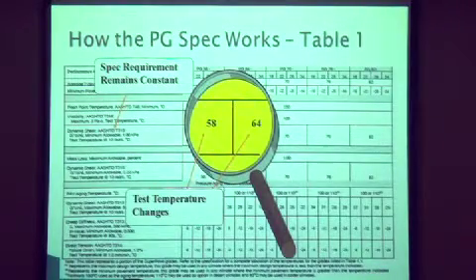The specifications that were produced are in the AASHTO M320, and you have a table where you have these different PG grades, and then what we have is a series of properties in these horizontal tables. So for example, here you have a dynamic shear stiffness. This number here, I know you can't read it on the slide, but it says 1 kilopascal, and the material has to be 1 kilopascal for this particular grade, 58, at 58 degrees C. This particular grade, it has to be 1 kilopascal at 64 degrees C, and so on. You basically are changing the temperature of the test rather than changing the property.